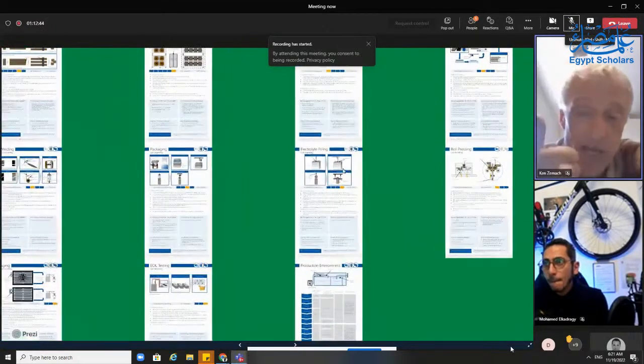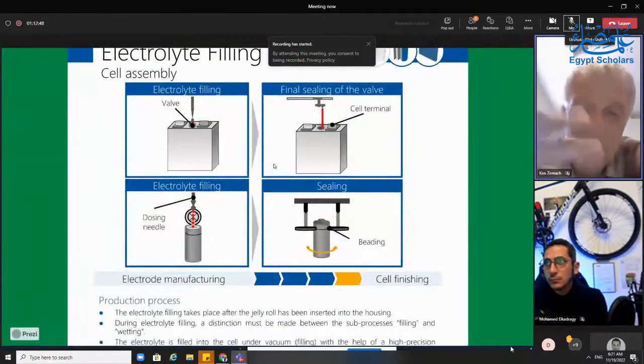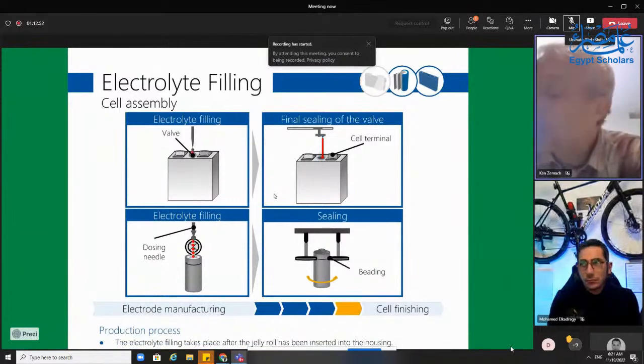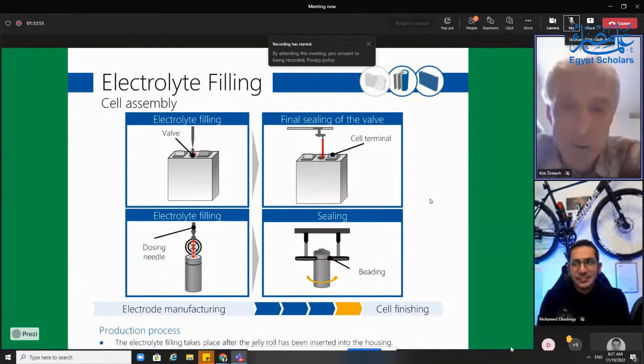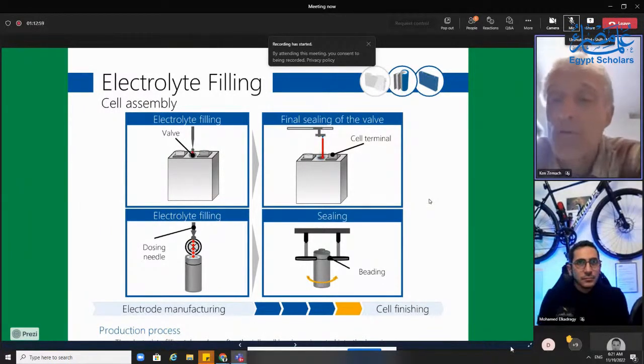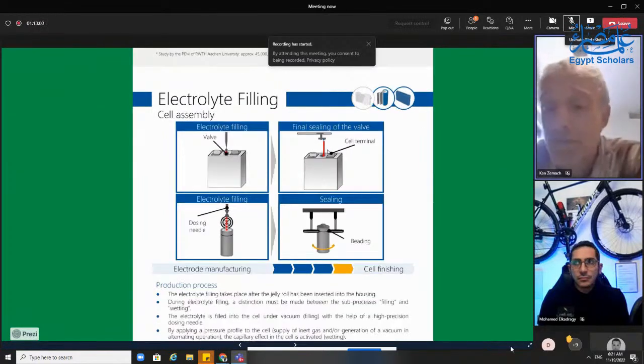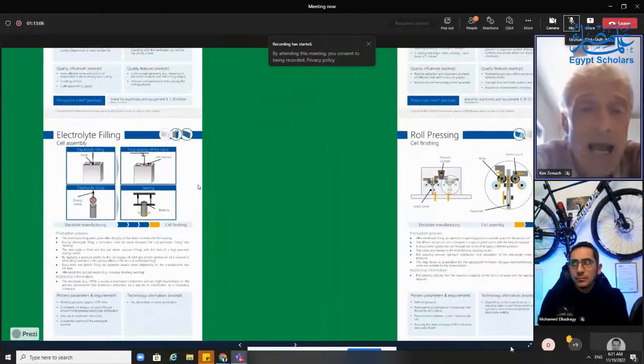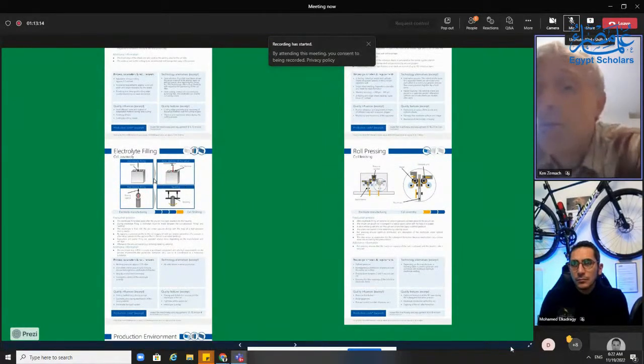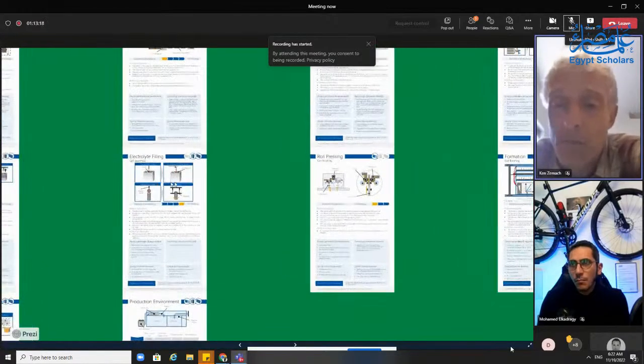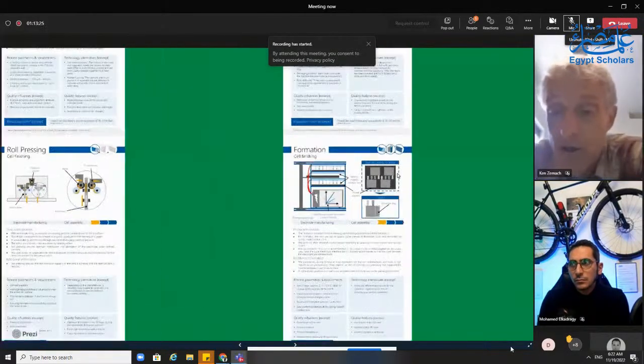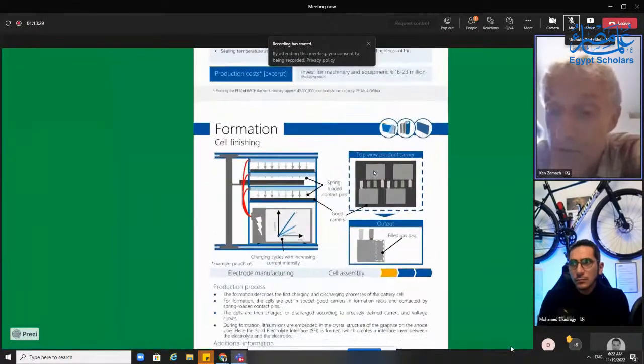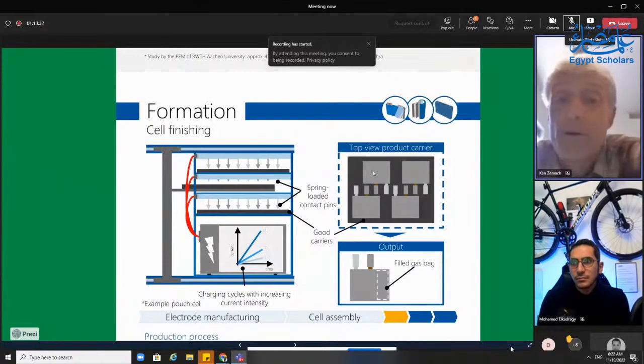So let's pretend you've gotten all the electrolyte that you want in your cylindrical cell or your prismatic cell or your pouch cell. You say, okay, great, now I can seal it up. Nope, you can't. Usually what you do before the final seal is a pre-charge, where you charge up your cell a little bit. Sometimes you charge to a voltage lower than full, sometimes you go up to full voltage. Now you're starting the first formation of the cell. You have to make sure all the electrolyte has soaked in. Sometimes soaking can take 30 hours. On large cells, you might have to wait 30 hours at an elevated temperature. Then you do this pre-charge, which is like the first stage of formation.